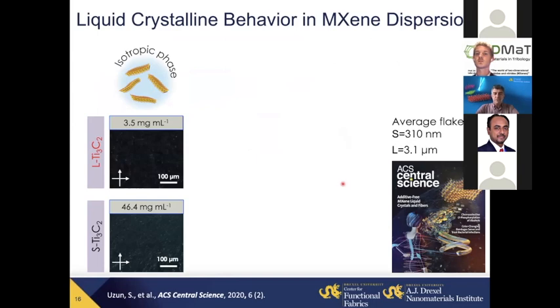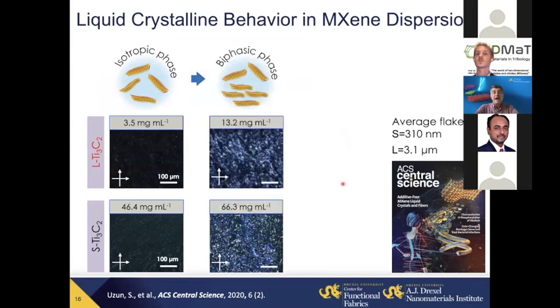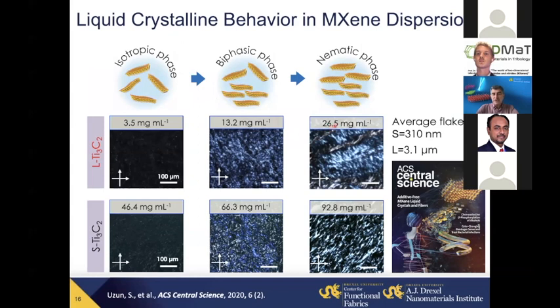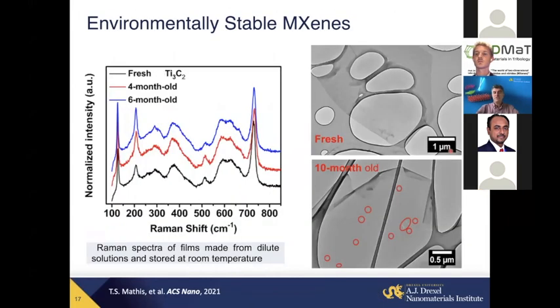But what may be also important for those of you interested in lubrication, tribology, coating is that above a certain concentration, these materials form liquid crystals. For example, for large particles, it already happens at about, say, over 10 milligram per milliliter. Smaller particles will require larger concentration, but if you go even to a bit higher concentration, for example, 26 milligram per milliliter, you can form a nematic phase. So basically, even in the liquid, all these particles align relative to each other. They cannot rotate freely anymore. And as a result, we get ordered particles, which again can be used to produce uniform coating on the surface.